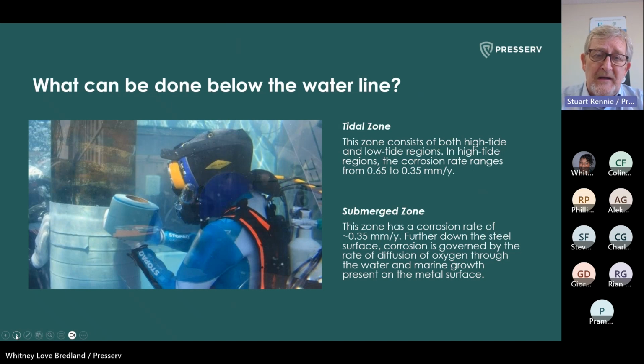Where we've got a marine application, the splash zone can then be broken down to what we call the tidal zone. So this is high tide, low tide areas. Sometimes it's submerged, other times it's not. And again, quite an alarmingly high corrosion rate per annum, 0.65 to 0.35. But again, these three areas we've spoken about before, perfectly treatable using StopAq.